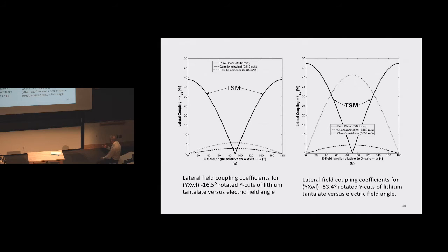For this particular representation, the psi angle necessary on this one is the psi angle over here, where you're exciting nothing more than the transverse shear mode here. And this represents 2 different cuts, minus 16.5 degrees and a minus 83.4 degree cut, both giving rise to a temperature-compensated shear mode. There's the velocity of the mode.